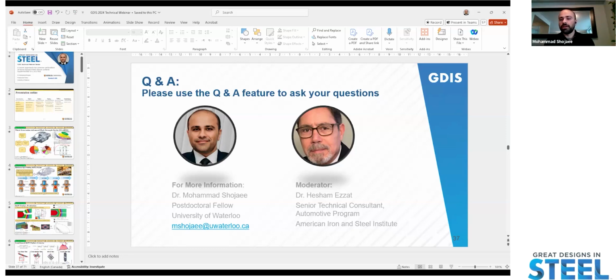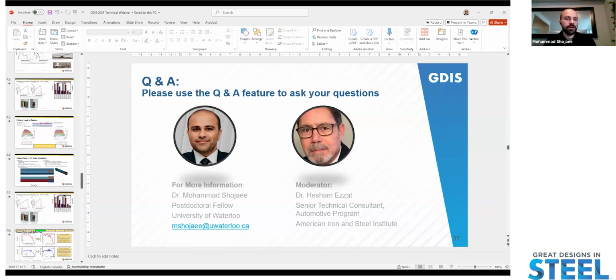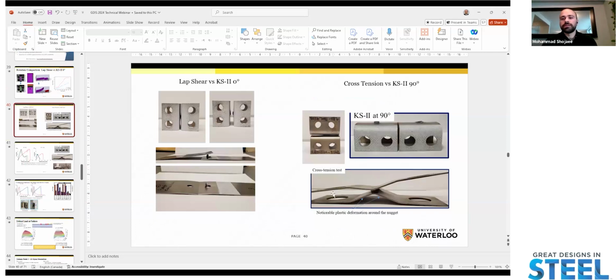Our tests are not perfect, like the coupons deform. For example, I can show here, we have the cross-tension test being a standard test on the right-hand side. You can see that in the case of a softer steel, so let's say 980, I'm not saying 980 is a soft steel, but relatively lower strengths, we get a lot of deformation on the base metal. And that base metal deformation is contributing to the energy absorption capability that we're attributing to the spot weld. So that's not necessarily the case. These 2 concepts are intertwined, and we can distinguish them by performing tests such as the KS2 test, which brings a much better defined boundary condition and is able to distinguish those properties of the spot weld and separate them from that of the base metal.